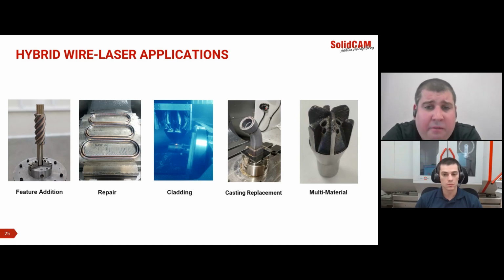And then one of the big advantages of Meltio is the fact that we can do multiple materials. We have the ability to switch between two different wires on the fly, not at the same time, but basically you can start out with one material and then switch. It takes about 5 seconds to switch between materials. So even on a given layer, you can have two different materials and go back and forth. In this multi-material example, some of the peripheral edges are in a harder alloy. One of the caveats: the materials must be compatible for welding. So, a lot of stainless and Inconel blends, as well as ferrous steel and stainless blends.